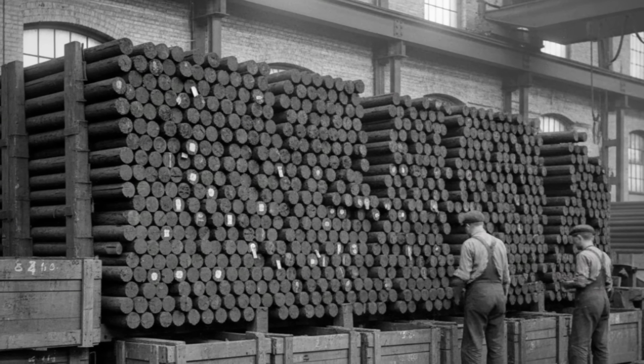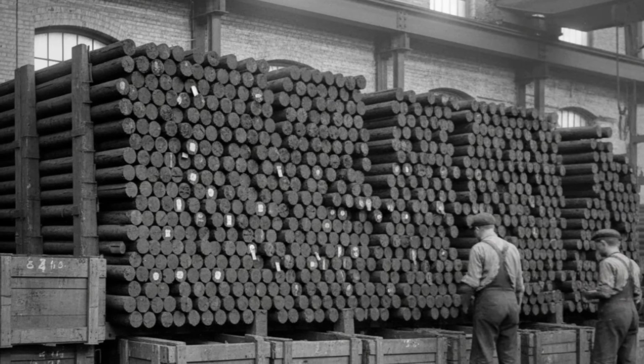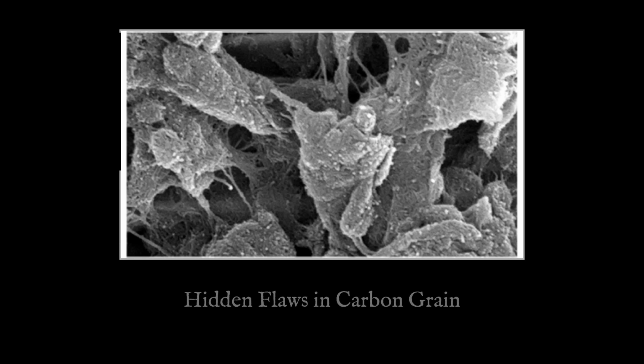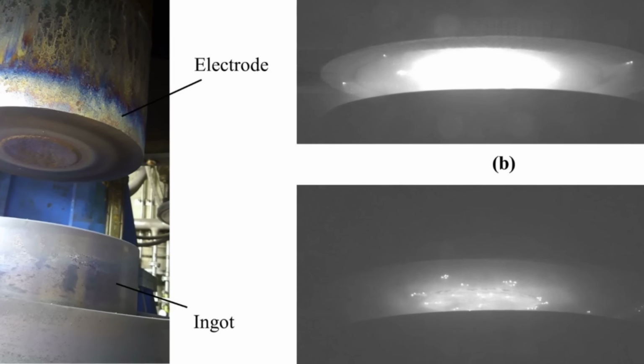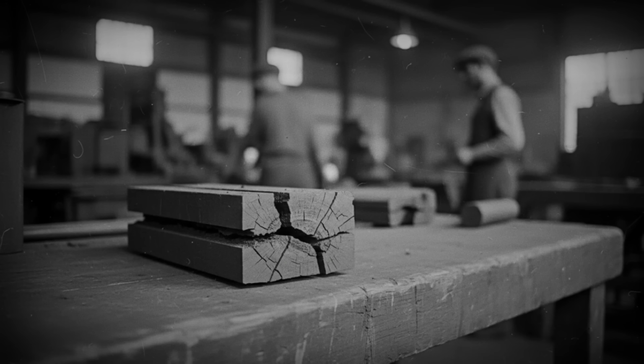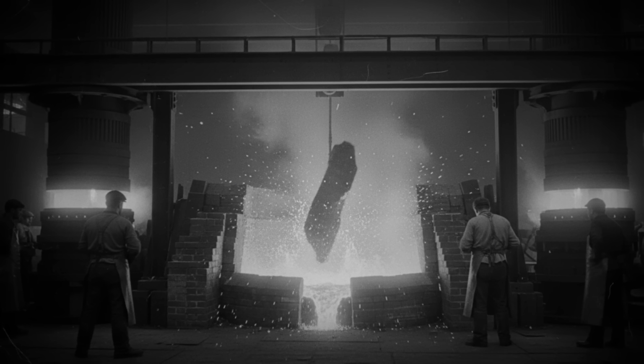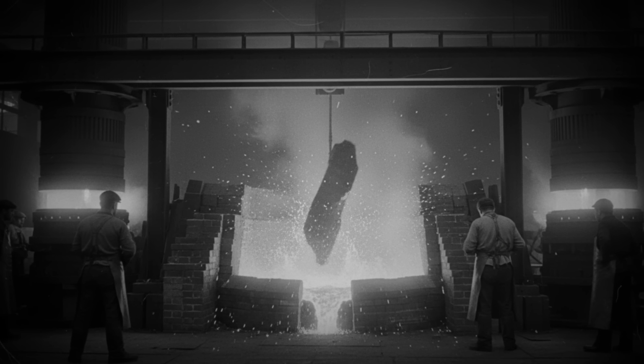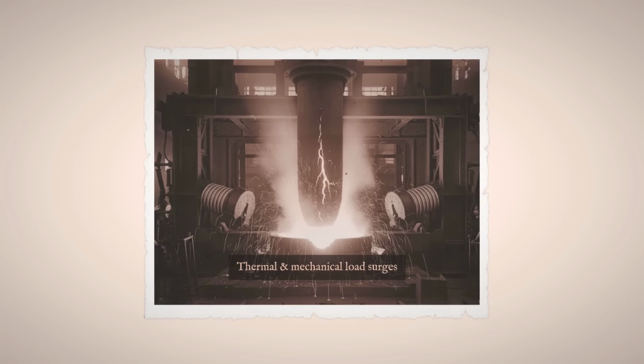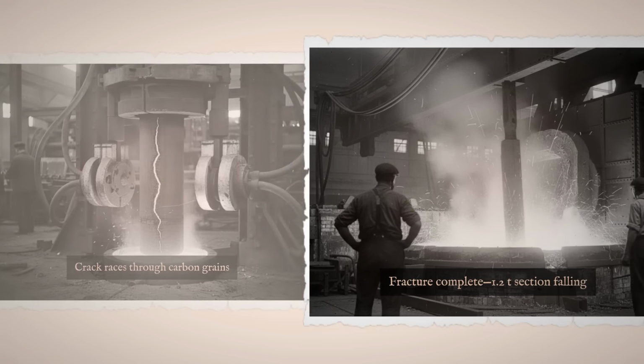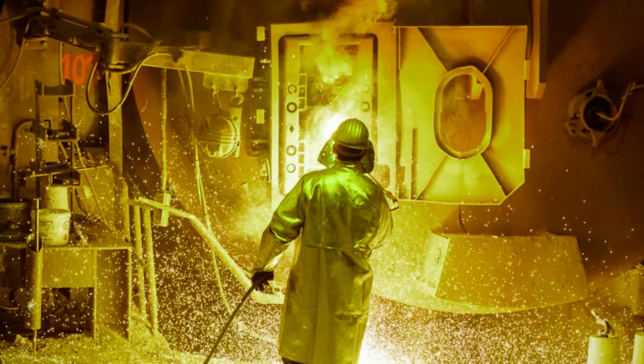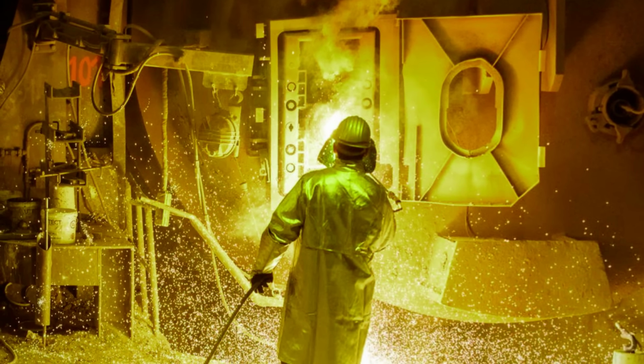Carbon electrodes manufactured in the first years of American arc furnace production had grain structure inconsistencies that could not be detected before installation. A column under current load and thermal stress could fracture along an internal grain boundary that showed no surface defect. The fracture propagated under the combined mechanical and thermal load of the arc cycle, and when it completed, the lower section of the electrode dropped into the steel charge below.